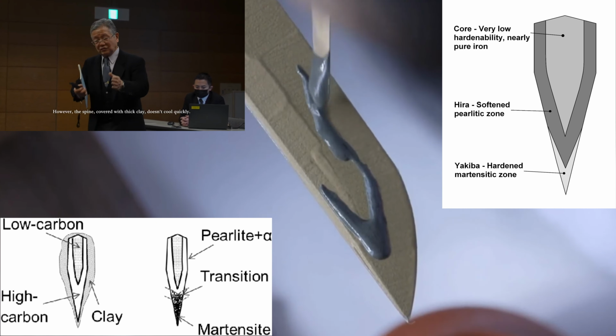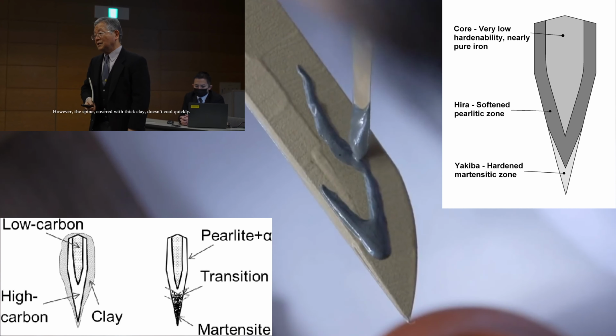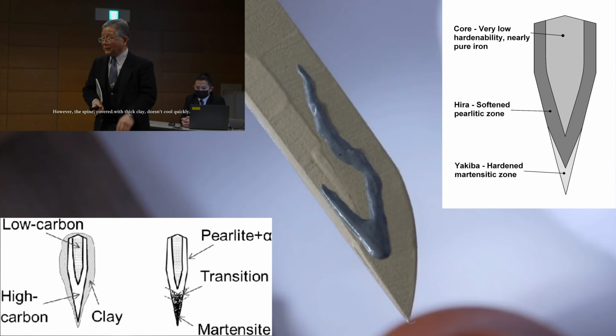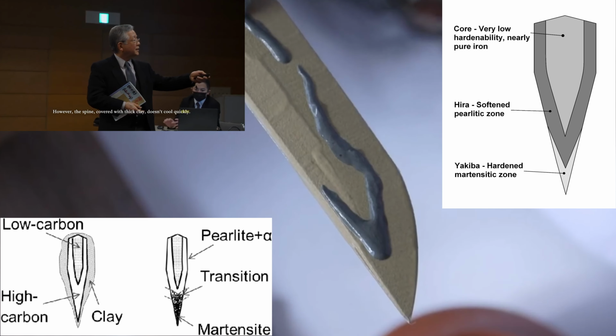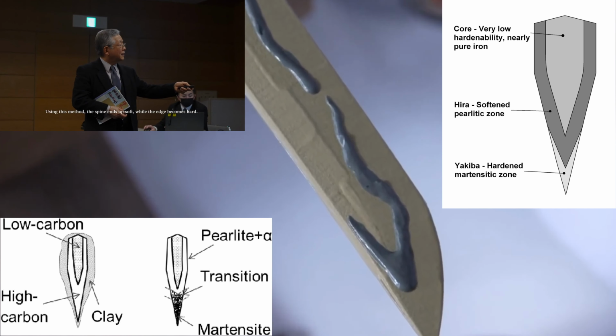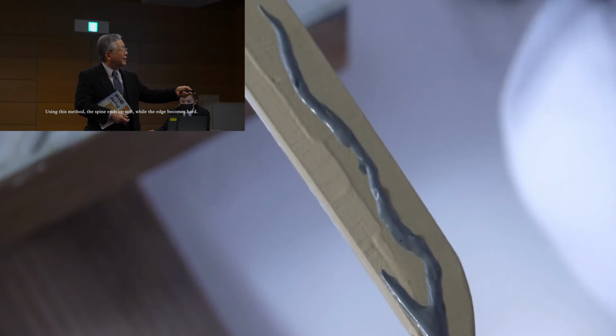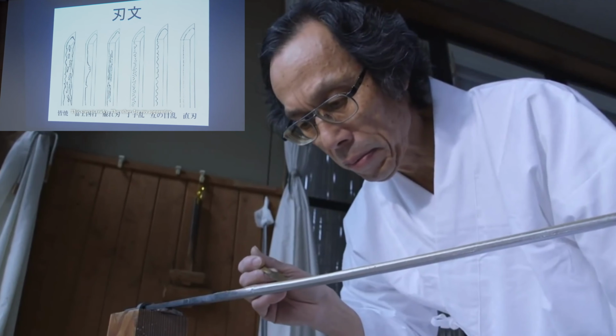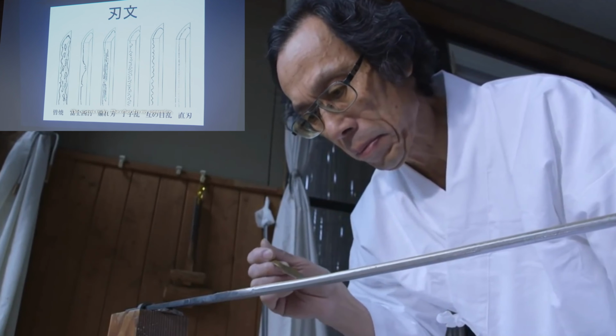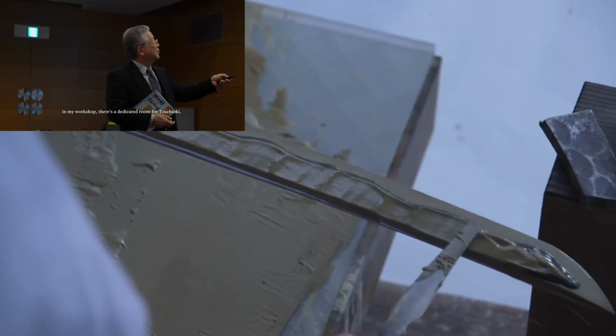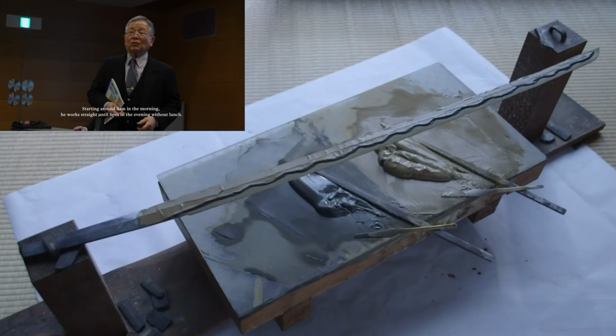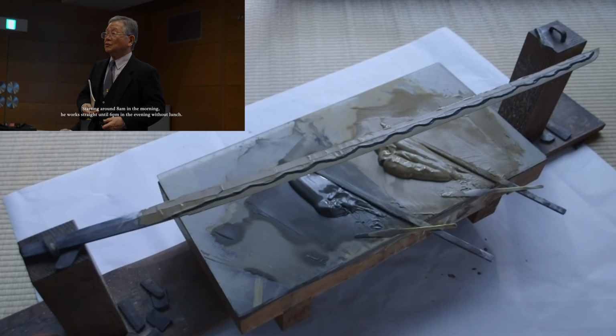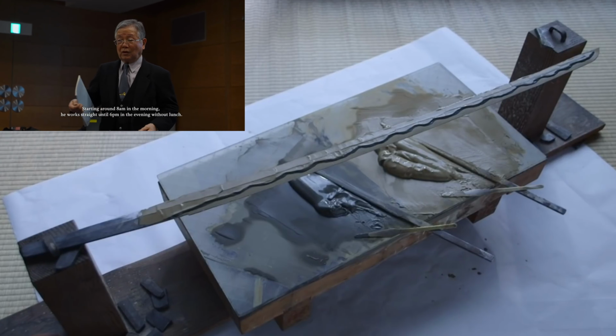During the differential heat treatment, the clay coating on the back of the sword reduces the cooling speed of the red hot metal when it is plunged into the water, and allows the steel to turn into pearlite, a soft structure consisting of cementite and ferrite laminations. On the other hand, the exposed edge cools very rapidly, changing into a phase called martensite, which is nearly as hard and brittle as glass.